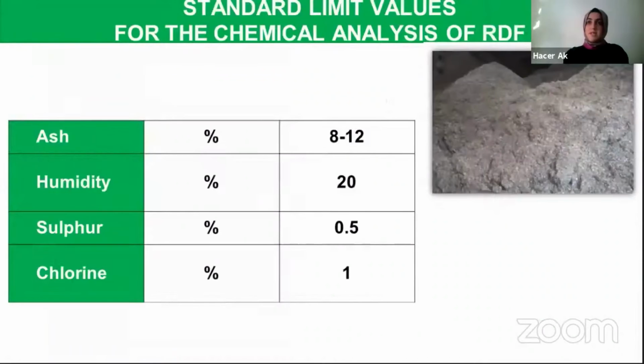Here we see the standard limit values for the chemical analysis of RDF summarized in the table. Moisture content, calorific value, chlorine, and sulfur content are the most important parameters. Higher chlorine content weakens the 2, 7, and 28 days compressive strength of concrete, thus weakening the cement. Nitrogen and sulfur have lower values in RDF compared to fossil fuels, thus the formation of nitrogen and sulfur oxides decreases with the use of RDF in cement plants.